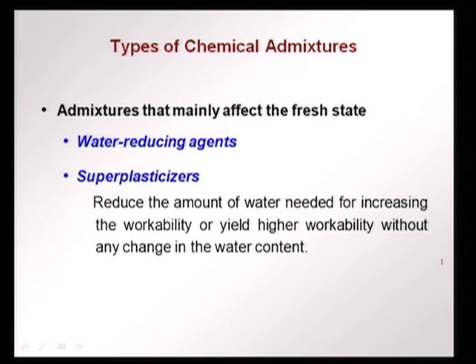So the first class of chemical admixtures are those that affect the fresh state, and here we have water reducing agents and superplasticizers. These reduce the amount of water needed for increasing workability. So, suppose you want higher workability because of congested reinforcement, slender elements and places which cannot be vibrated well, then without increasing the amount of water we can have higher workability when we add a water reducer or a superplasticizer. On the other hand, if we have the same water content in two different concretes, but one has a superplasticizer or a water reducing agent, you will end up having much higher workability. Therefore, again we can increase the workability without changing the water content, and in some cases for the given workability we can reduce water, so that will increase the strength and the durability.